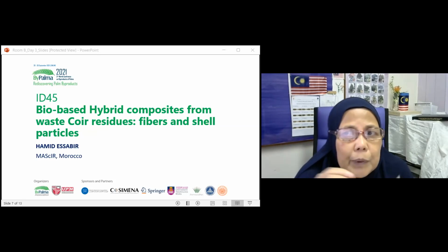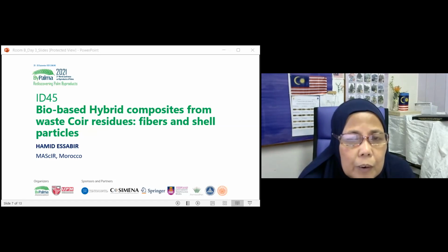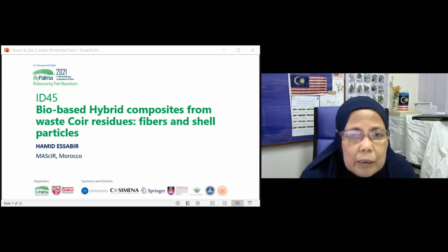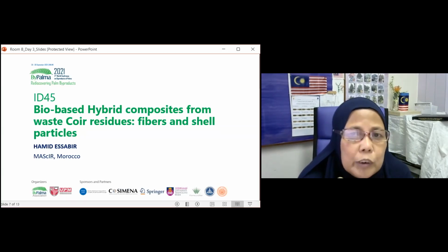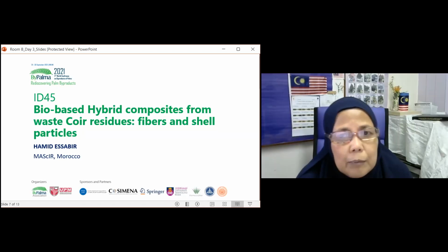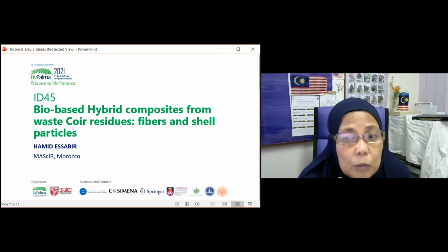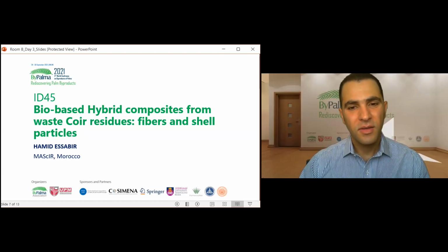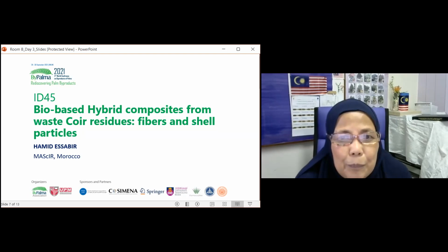After we have prepared the sample, we break it down into a smaller pellet form. And when we do the board itself, we measure the amount into a mold and press it. We do have the capability to do extrusion, but for this particular test, we just want a flat surface. But of course, if you want to show whether this product is workable or not, then it works just like normal plastic pellets for extrusion. So it just depends on what you want to test it for. Yeah, sure. Thank you so much.